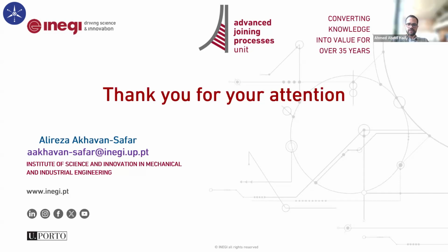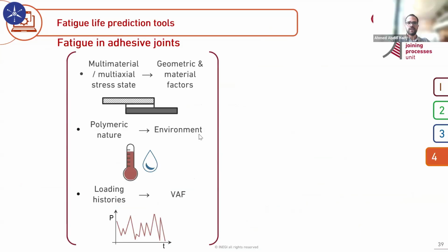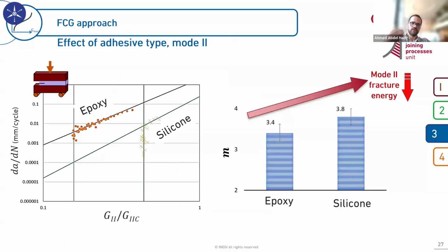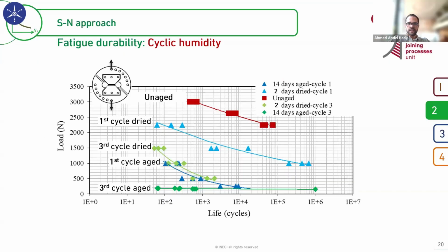Thanks for answering this, but I think the main point from Chaula is that the sample now faces two fatigue cases. The first one is the stresses that come from the humidity cycle, where you increase the humidity, reduce it, increase it, and reduce it. This will cause a little bit of strength degradation. The second process is the fatigue loading: loading, unloading, loading, unloading, which means the strength will also degrade because of this. So the question is, how can we decouple this effect? If we have a 10% reduction due to humidity and 10% reduction due to fatigue loading, how do we decouple this? I don't know if the question is clear.